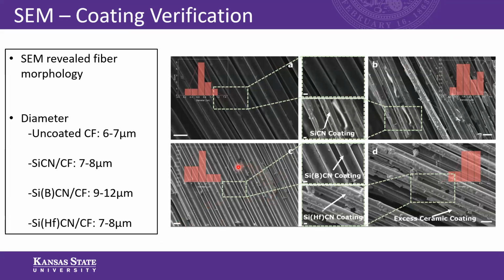SiBCN samples similarly received an average fiber diameter of 9 to 12 micrometers, and SiHFCN coated samples obtained an average fiber diameter of 7 to 8 micrometers. So as I mentioned, this increase in diameter verifies that the fibers were in fact coated.